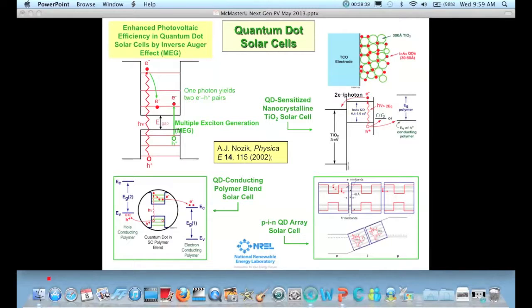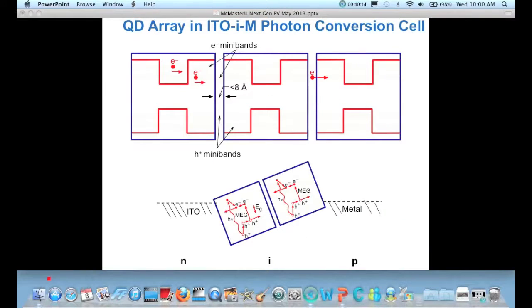Or you can have a hybrid cell where you immerse the quantum dots into a matrix of either C60 with a hole-conducting polymer, or generally have 2 phases where the dots are dispersed, and then when you excite the dot and create multiple electron hole pairs, you collect them in the 2 phases. So this would be the electron conducting phase and the hole conducting phase, and you can build a device that way. What we've been focused on are these arrays, where you self-assemble the dots into an array.